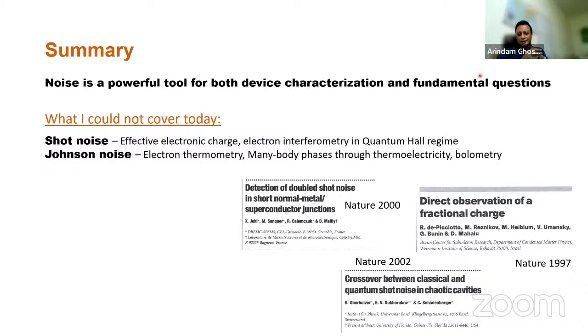It's usually because of crystallinity. So we actually found that the gallium arsenide is still noisy because it has these dopants randomly distributed in the modulation layer, which is a little bit away from the actual two-dimensional electron gas. But actually, we found that the lowest noise is in the phosphorus doped silicon devices, where, because phosphorus is strongly bound, we found the noise is extremely weak. And we realized that in order to decrease noise in silicon or any semiconductor, the crystalline environment is the key.